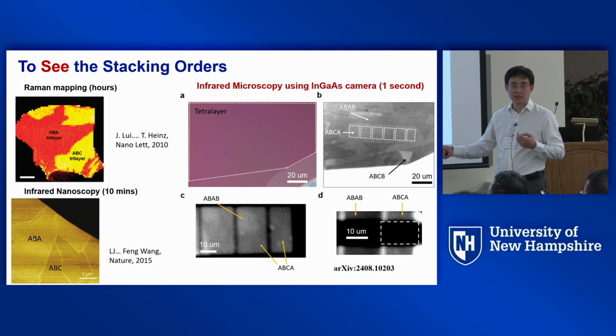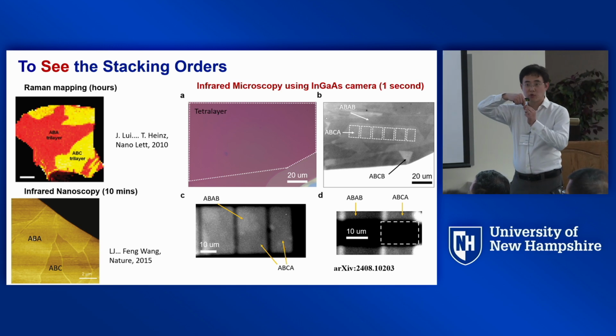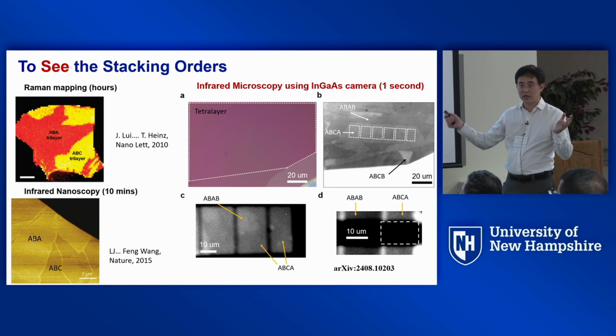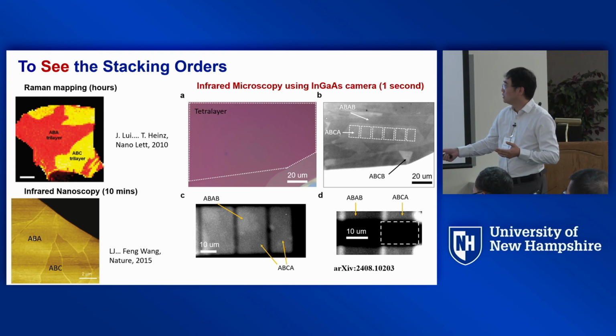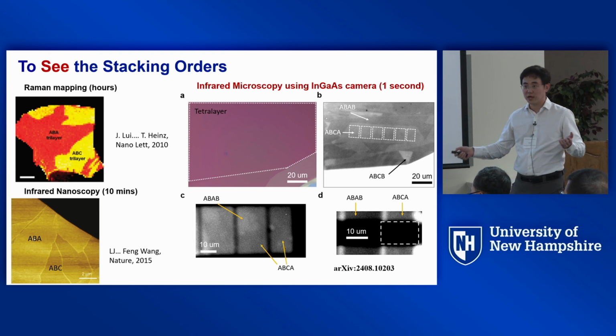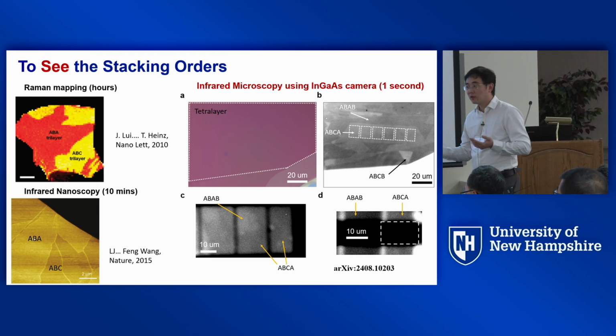And when I was a PhD student working with Feng Wang, we took another approach, using infrared light coupled to an AFM tip. So we get the spatial resolution down to 10 nanometers, and we can also tell the two stacking orders apart because they have different infrared conductivity.